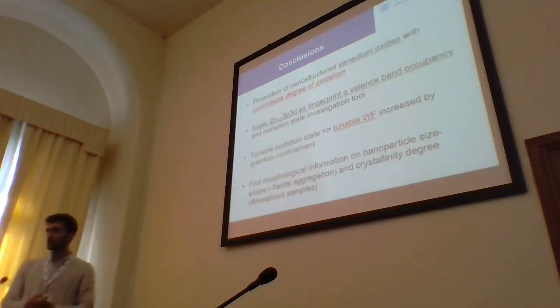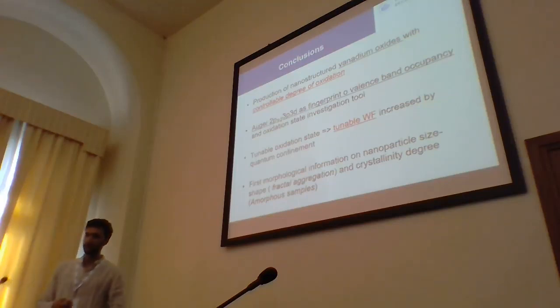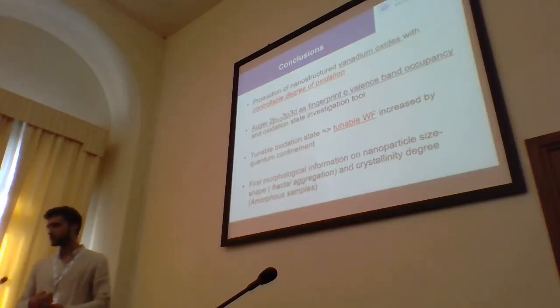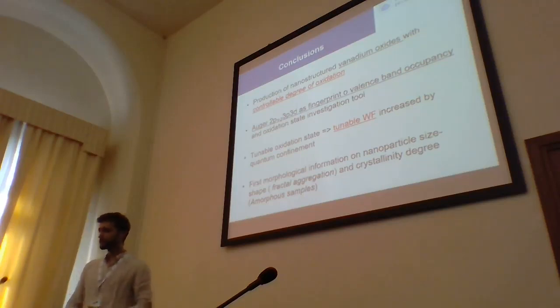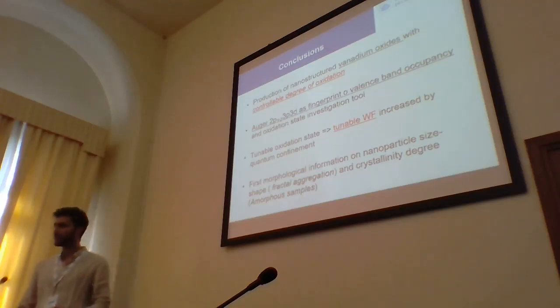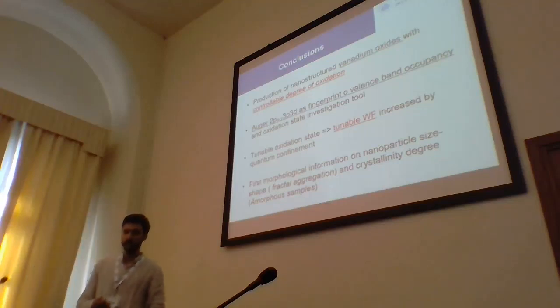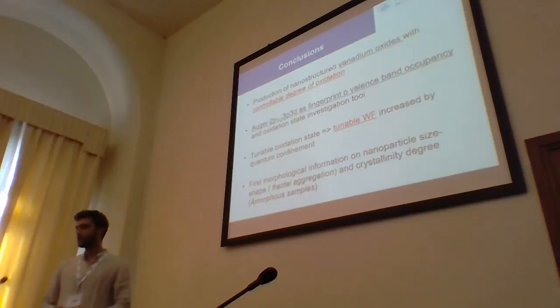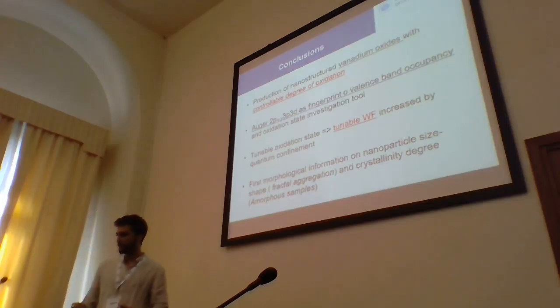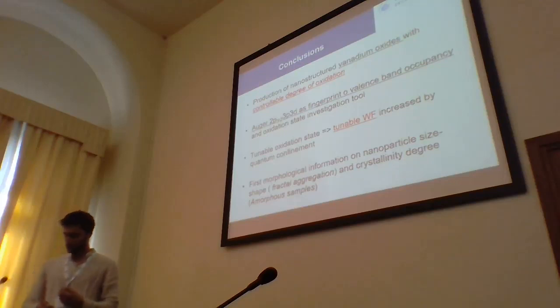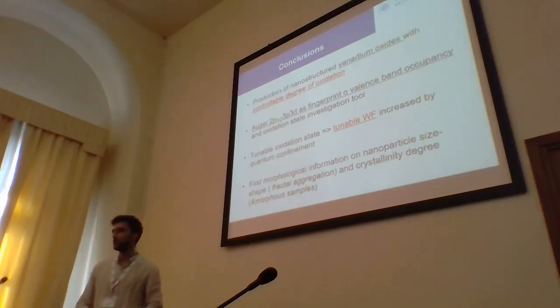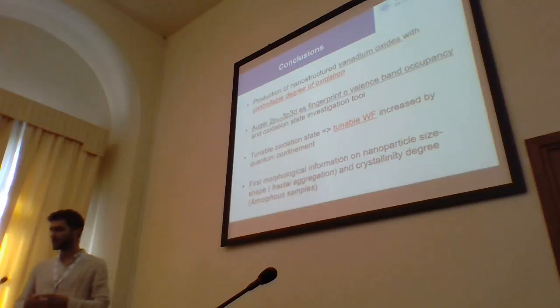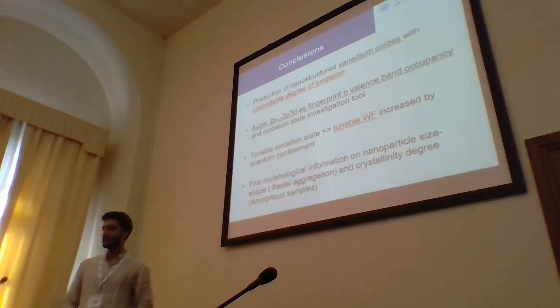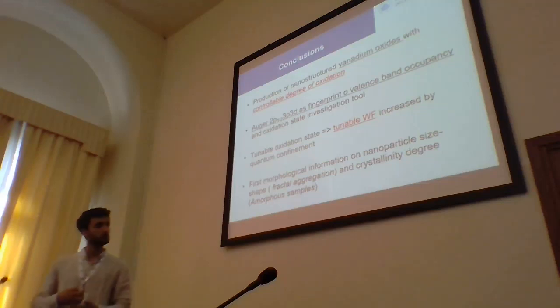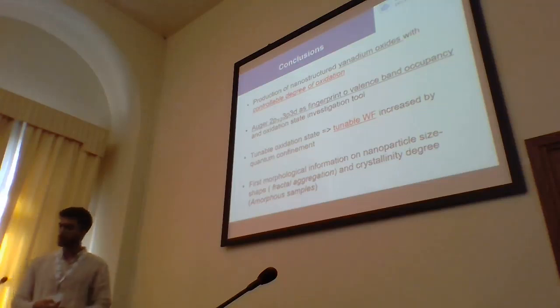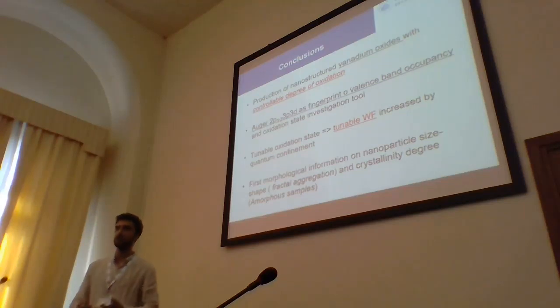In conclusion, I showed you that we can produce vanadium nanostructured thin films with controllable oxidation state. I showed you that using photoemission spectroscopy, we can investigate the valence band structure and point out some interesting features, and that as a consequence of the oxidation state control, we are also able to control the work function of our sample. And lastly, I showed you that our samples are amorphous, and that one should never blindly trust microscopy.